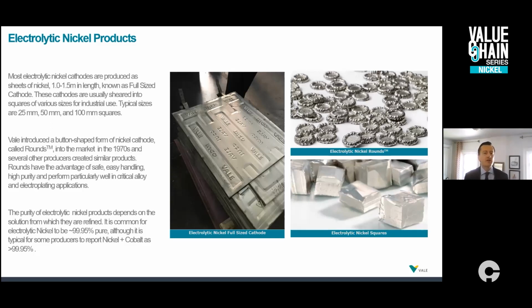Finishing up electrolytic nickel. The majority of electrolytically refined nickel is produced as a slab you see here, give or take a square meter in size, and give or take 10 to 15 millimeters thick. Most of the time, almost all of the time, that material is then sheared into smaller square pieces. So whether it's 1 inch square, as you see in the bottom right photo, 2 inches square or 4 inches square, those are the most common sizes.